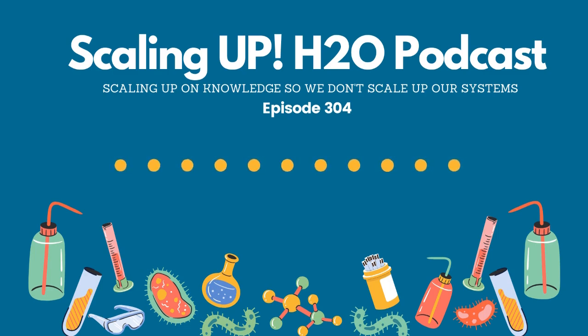I set them all out flat on our bench, and then we have to use the envelopes that you gave us to identify the serial number to the coupon, and then we start weighing each coupon, again, down to the 10,000th of a gram. That's very, very specific, and of course, that's not your ordinary scale. These are special metallurgical scales, and then once that's done, we take a final picture of what that coupon looks like front and back after it's cleaned, and then we start doing math.